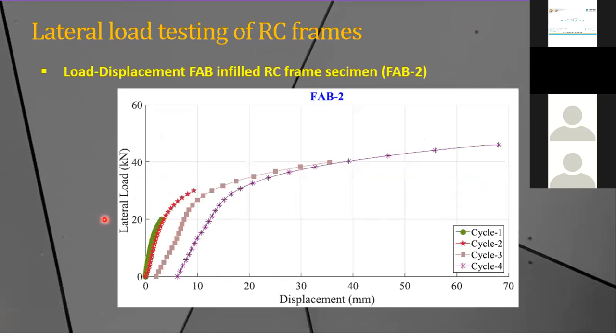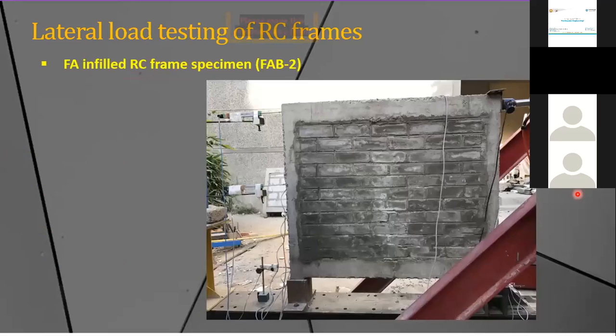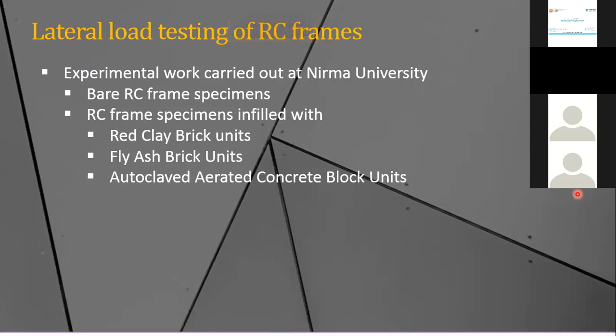Now with this load versus deformation plot, you have to calculate the area below this plot, which will give you a strain energy. So the area below this curve becomes the strain energy, and that energy got dissipated. Of course, this is a half cycle, so we have modified the equation which I showed earlier with an energy equivalence. We modified that equation for a half cycle, and then we calculated, using numerical integration, the energy stored in the experimental setup through that load versus deformation plot. Then we equated that energy dissipation for a half cycle with the energy dissipation in viscous damping, as given in a standardized form for a viscous damping element.